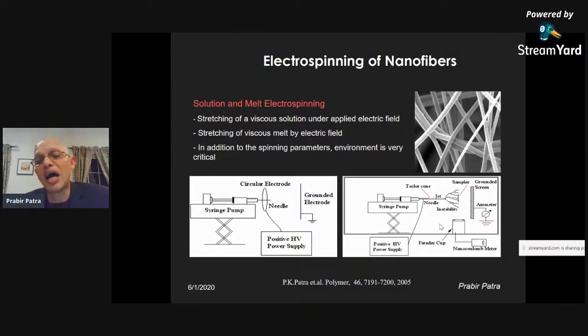So we calculated by our own design. We had a Faraday cup, we had a nanocoulomb meter, and we connected those to the fiber, and we measured the charge as 35 nanocoulomb per milligram. So think about this. A single 100 nanometer collagen-like fiber has a charge of 35 nanocoulomb per milligram. Measuring the fiber charge of that small density itself is a feat. So it was very early, and this work was represented very well in the community.